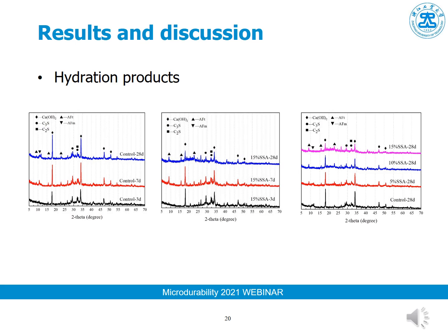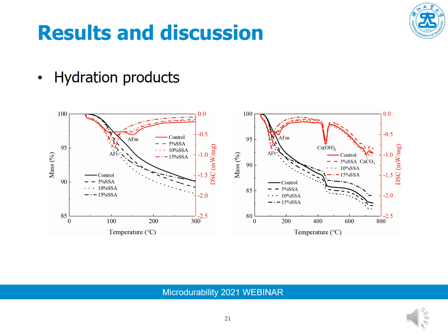So it might be true that the sulfates in the sewage sludge ash will cause volume stability problems to the cement-based materials. So we did some microstructure analysis, and this is the XRD results. And from the last figure, we can see that with more sewage sludge ash, we can see more ettringite and less calcium hydroxide. From the results of the TG tests and the DSC tests, we also can see that more ettringite was formed in the cement paste with more sewage sludge ash. So actually, the formation of the ettringite was the reason for the expansion during the volume deformation tests, such as the autogenous shrinkage tests and the potential expansion tests.